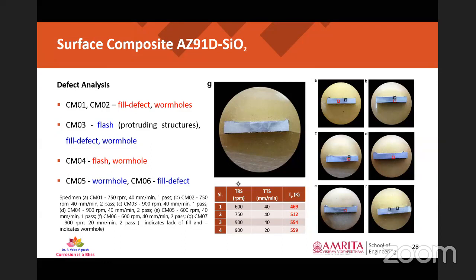Okay, yeah. So with this, we confirmed that the optimum process parameters for fabricating surface composites out of AZ91D of 4 mm thickness is 900 rpm as tool rotation speed, 20 mm per minute as tool traverse speed, and for 2 passes. Okay, yeah. So with this, we'll just move towards characterization of microstructure.